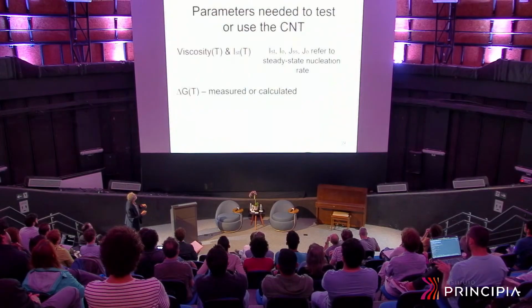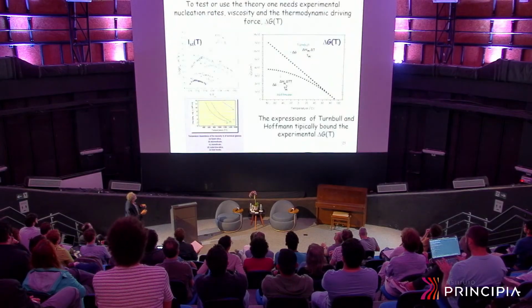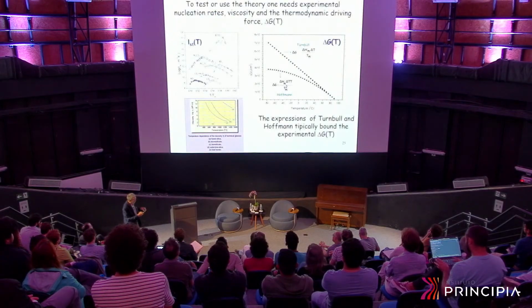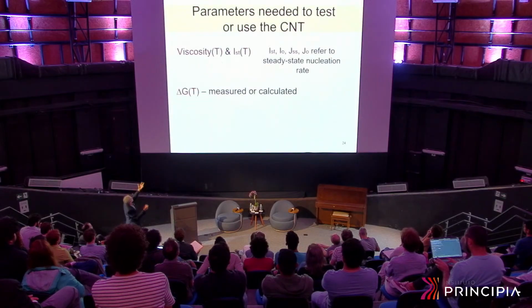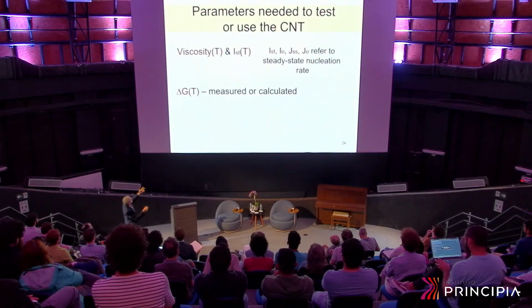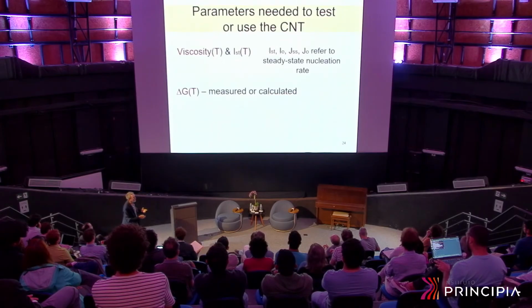All right. So, if you have the viscosity for the diffusivity, and you measure nucleation rates, and you measure delta G, you can test whether this theory works or not.